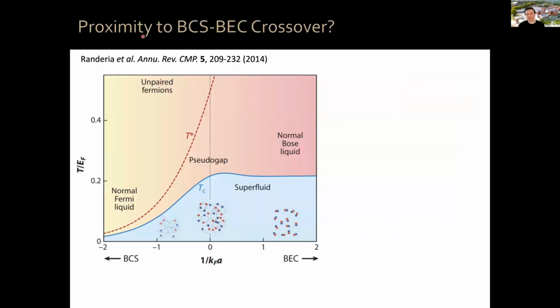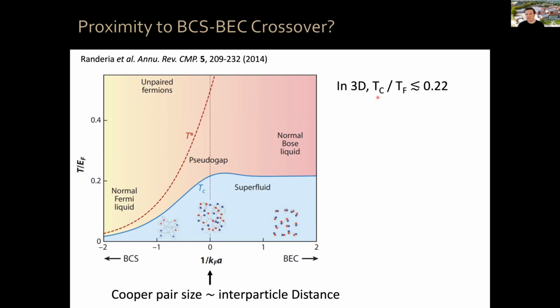So this is very reminiscent of the situation that you have when you have a BCS to BEC crossover, okay? This is a plot from Randeria and Taylor's review about BCS-BEC crossover, okay? In the BCS limit, your Cooper pairs are much larger than your average interparticle distance. In the BEC limit, you have very tightly bound molecules. The crossover typically occurs when these two length scales are similar, when the Cooper pair size is of the same order as the interparticle distance. Now, in 3 dimensions, the maximum value of Tc over your Fermi temperature TF is 0.22, and it happens at the crossover.